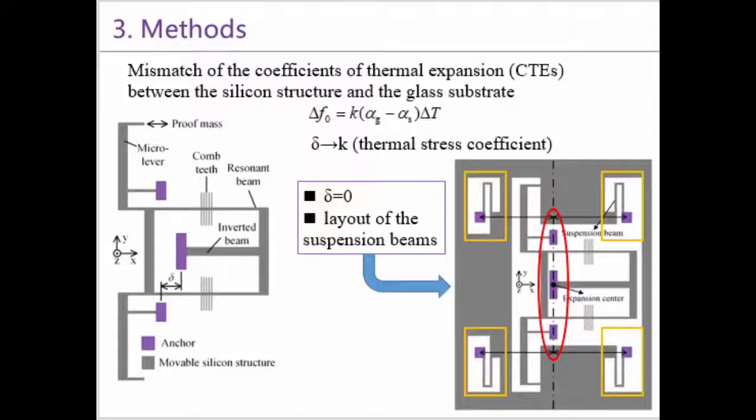The MRA was fabricated by silicon-on-glass process. Since the coefficient of thermal expansion of the glass substrate is larger than that of the silicon structure, the x-axis distance between the anchors will increase as the temperature rises. In this case, the natural frequency of the resonant beam will increase due to the tensile force. If the distance is zero, the thermal stress along the x-axis can be decreased greatly.